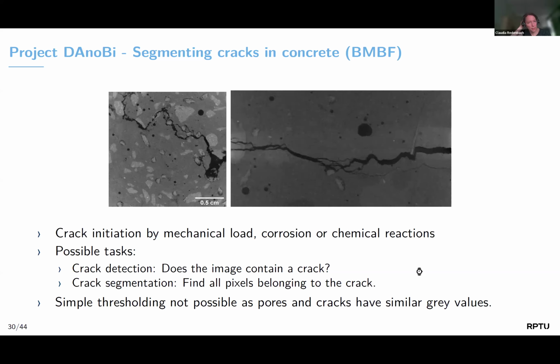Here we clearly see that simple thresholding does not do the job because there are other things present here, for instance, like air pores that share the same gray value distribution as the cracks, and therefore just by thresholding we would get everything. But we are just interested in that crack here.